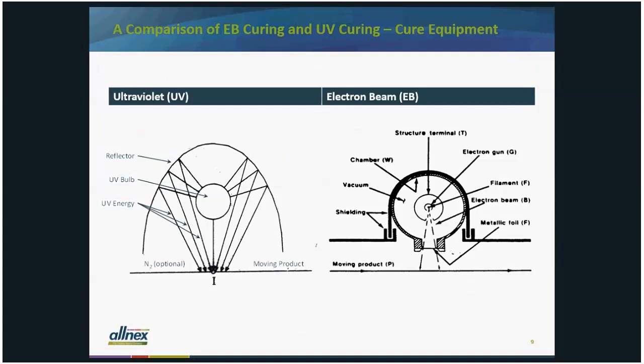In contrast, the electron beam source is usually a filament of metal that's heated, and electrons are extracted from the filament and accelerated towards the substrate using a voltage drop. They pass through a thin metallic foil window and then strike your coating, which then cures. Because some electrons may pass through the substrate and coating into other materials, which is a process which can create some high energy radiation, shielding is required to block this radiation and protect workers.